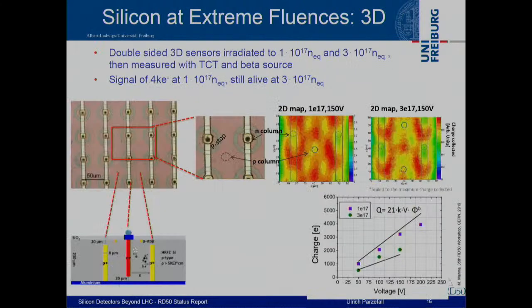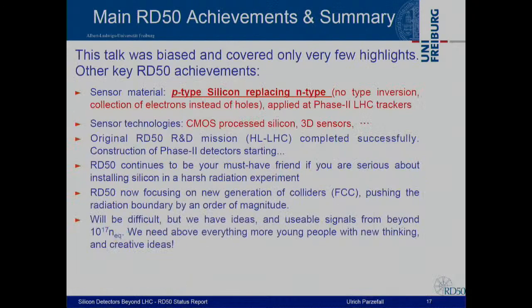And then last result plot is from 3D detectors made at CNM, and there, maybe just to summarize here on this, you can see that you still get a reasonable charge for 1 times 10 to the 17 or 3 times 10 to the 17 neutron equivalent. And if you look at this 2D map, you see that quite clearly you can resolve, like in Lena's measurements earlier, the 3D structure of the sensor. These sensors are still alive at 3 times 10 to the 17.